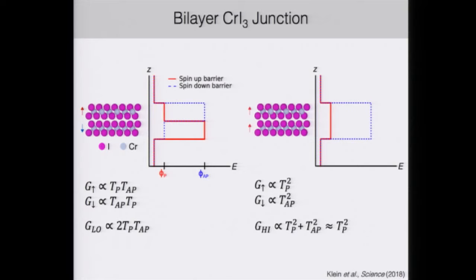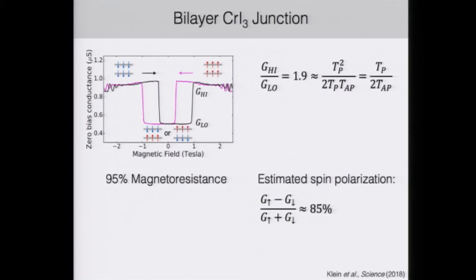And in contrast, in the fully aligned state, the spins that are pointing spin up and aligned with the barrier have a very easy way to tunnel across, and this will give rise to an overall increased conductance and increased spin polarization through the barrier. So we can then look at the bilayer data and estimate that the spin polarization in this fully aligned case is close to 85% based on our simple model.